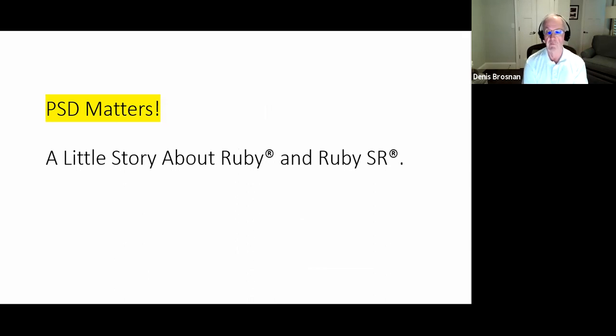I want to tell you a little story about a refractory product called Ruby. It was an alumina chrome brick, about 90% alumina and about 8 or 9% chrome by my memory, chromic oxide. It was red in color, like a ruby, because it was a fired brick and it formed that alumina chrome solid solution, having that red color. When it was initially used in incinerator service, it exhibited a fair amount of spalling in that particular service. And so someone at the manufacturer's location, I was told, decided, what if we underfire the Ruby? What if we maintain finer pore sizes in the product? Would it be better? And it was. And so then they called it Ruby SR, spall resistant.